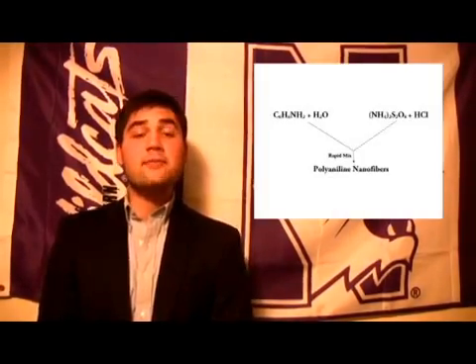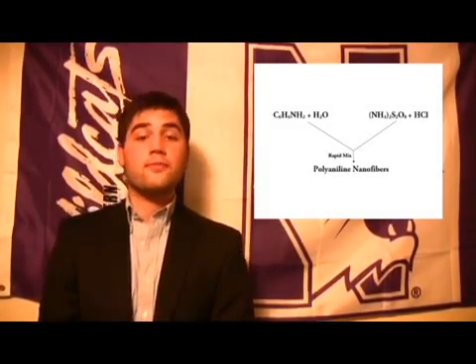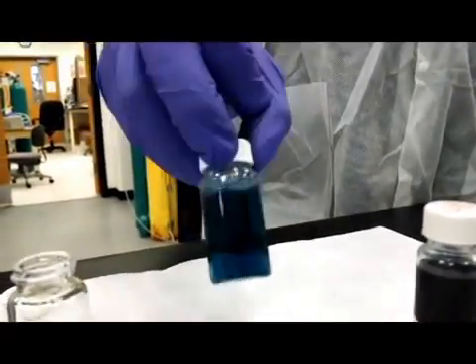If you're watching your weight and looking to burn a few extra calories, try rapid mixing. Using the same concentrations as before, dilute aniline monomer in distilled water — not chloroform. Pour this mixture into the same acidic ammonium persulfate used in the previous method, and then start shaking it like a Polaroid picture. By shaking it, the aniline monomer quickly and completely reacts with the dopant, allowing it to form nanofibers instead of worthless clumps.